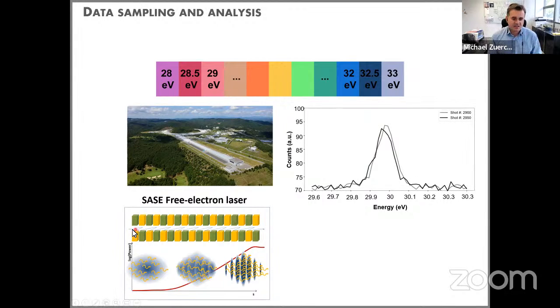Due to the Lorentz force, the electrons are forced into a quiver motion, and accelerated electrons emit radiation. If the kinetic energy of the electrons and the periodicity of the alternating magnetic fields are set correctly, you can make this radiate at X-ray photon energies. What makes a free electron laser, however, is that these undulators, these chains of magnets, are fairly long. There are several dozens of those magnets that the electrons are shot through. And now you get an enhancement effect.